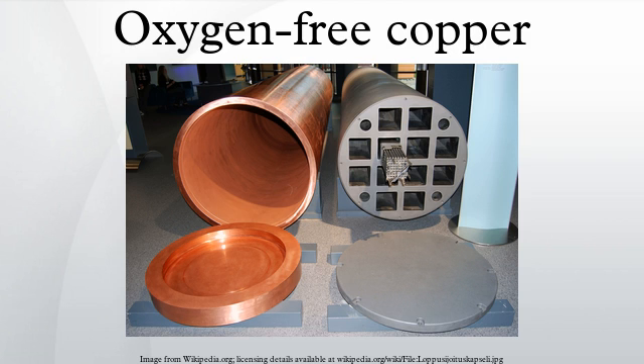The hydrogen diffuses through the copper and reacts with inclusions of Cu2O, forming H2O, which then forms pressurized water steam bubbles at the grain boundaries. This process can force the grains away from each other and is known as steam embrittlement. OFHC copper has been selected as a corrosion-resistant material for the overpack of spent nuclear fuel in the KBS-3 concept, developed in Sweden and Finland to dispose of high-level radioactive waste in crystalline rock formations.